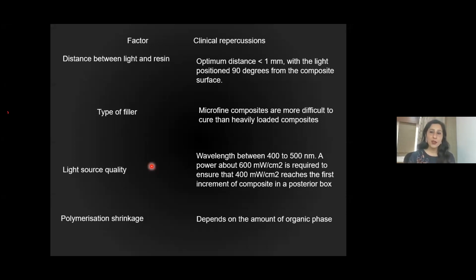The light source quality should always be checked. The wavelength should be between 400 to 500 nanometer, and ensure that your intensity is good enough. And halogen lights, I think you should discard them from your dental office because they do not give good light intensity. So it is always better to invest in an LED light cure probe. And you should also know the nanometer, as I told you, the wavelength that your light cure probe works on, and also the intensity of the light. So a good investment is a radiometer.